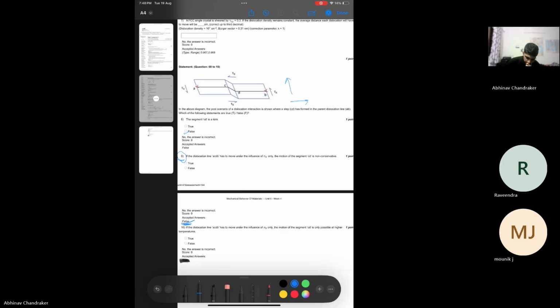One way to rationalize this answer is that if you have tau A only, then the slip will occur along tau A. So the component of the Burgers vector along tau A will be deciding the direction of slip, right? Here the component of the Burgers vector along tau A will be lying on this slip plane. So it is in the slip plane, so it can glide. We can consider it as a glide plane. So the motion will be conservative.